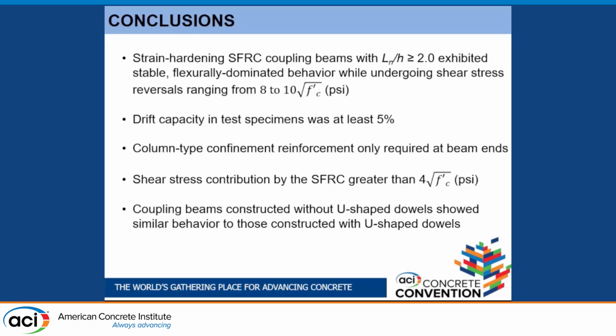We achieved a drift of at least 5% before we got a 20% strength decay. We only needed column-type confinement reinforcement at the ends, rather than over the entire coupling beam as required for diagonally reinforced coupling beams.